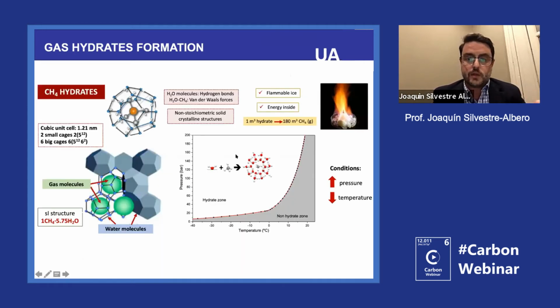So basically what we were trying to do in our research was to take advantage of the confinement effects in the cavities of the carbon and try to promote the nucleation and the growth of these hydrate molecules. If you see the phase diagram of the gas hydrates at 0 degrees, which is the temperature I will show you in our experiments, around 3 megapascals, so 30 bars, is the threshold pressure to go into the hydrate stability zone. So once you pass 3 megapascals, you must start seeing something. And our main goal was to do this type of process in the cavities of the carbon materials.